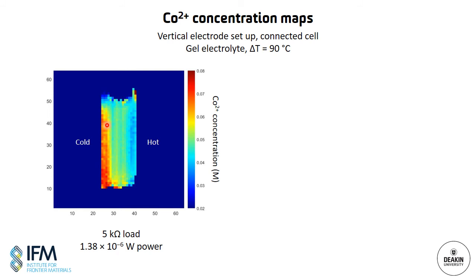So under this effect, we'd expect to see both types of cobalt species clustering on the cold side of the cell. And obviously the relaxation is dominated by the cobalt 2+, the paramagnetic species. We wouldn't expect to see this effect for the liquid sample because we have convection continuously mixing the species. But in the gel sample, we believe over time this can take place, and this is what we're seeing here.